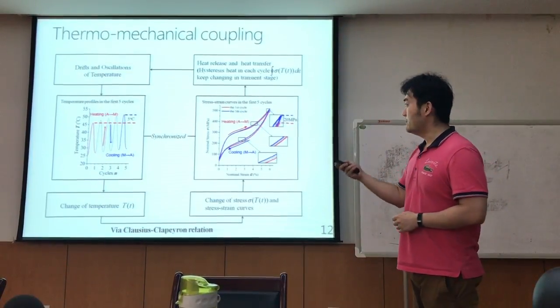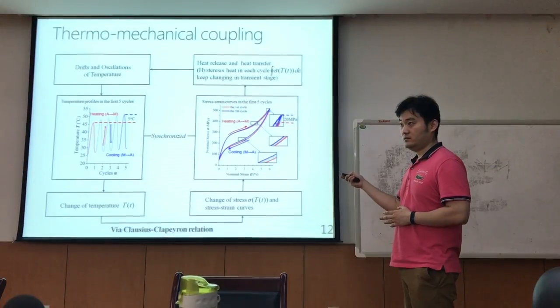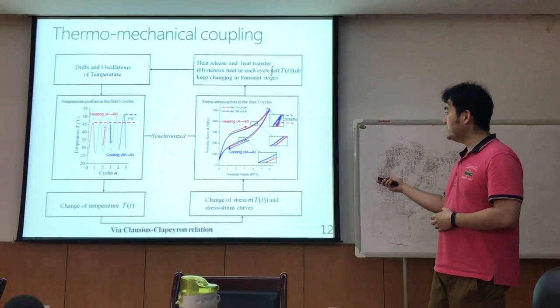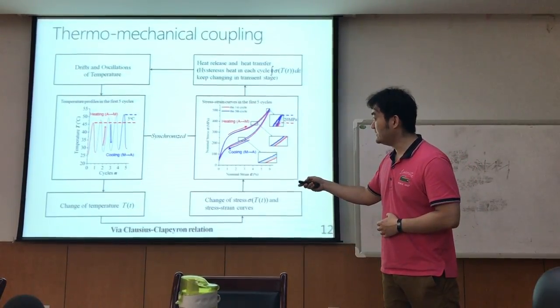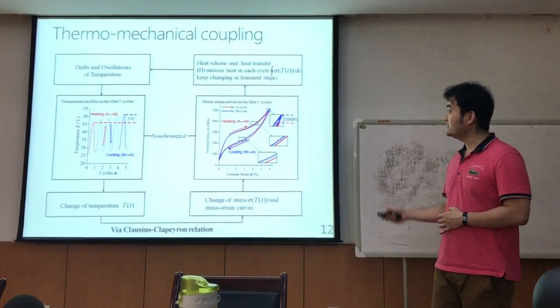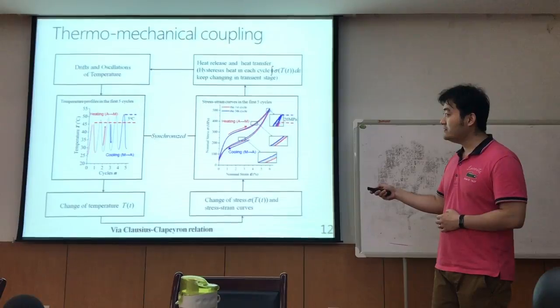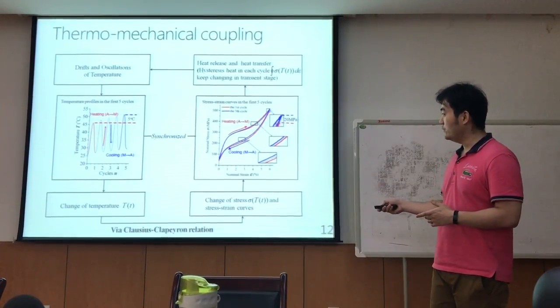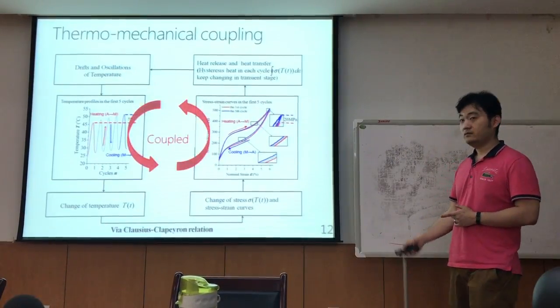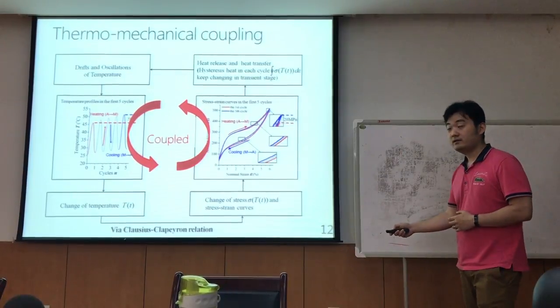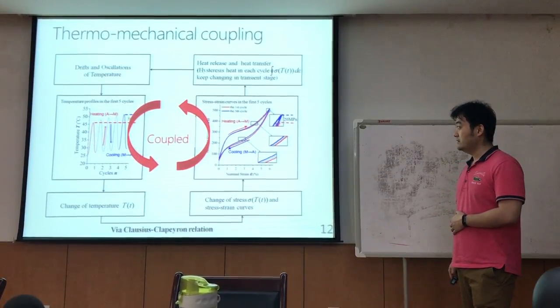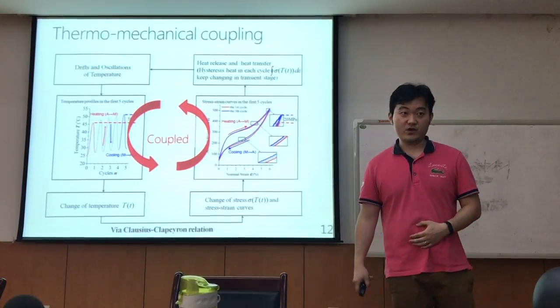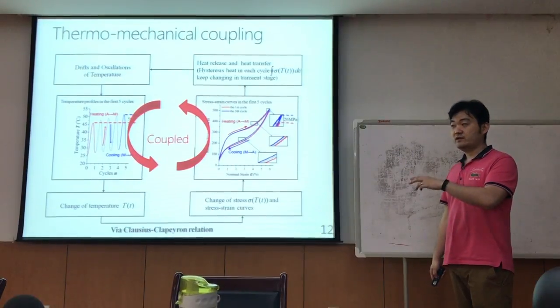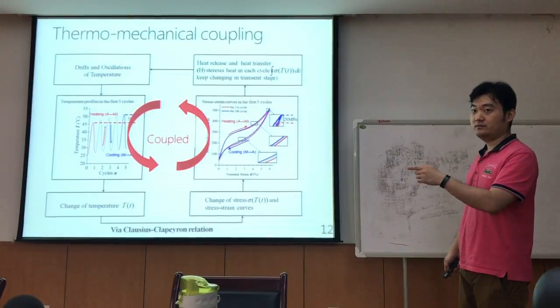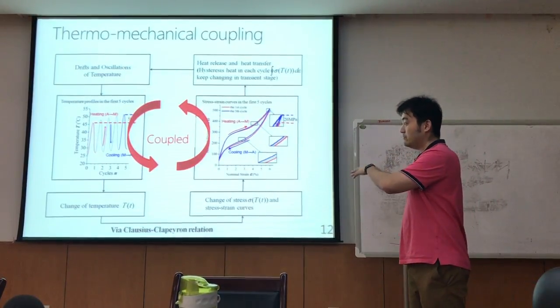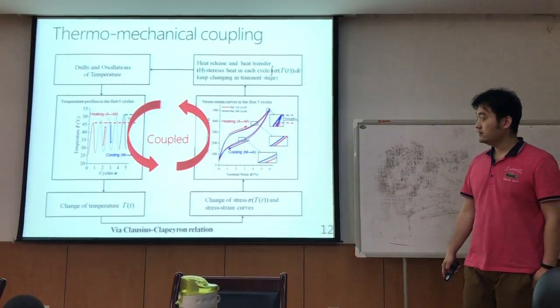So the heat source changes as the cyclic loading goes on. When the heat source changes, it will in turn affect the temperature variation. So the mechanical response will affect the thermal response. At the same time, the thermal response will affect the mechanical response. So they are coupled with each other via the Clausius-Clapeyron relation, which makes it a very complicated process. But this is a very good scientific problem. So we want to find out how this thermomechanical coupling process goes on.